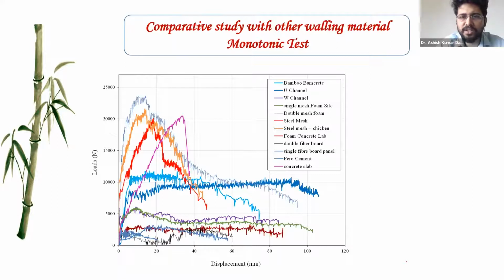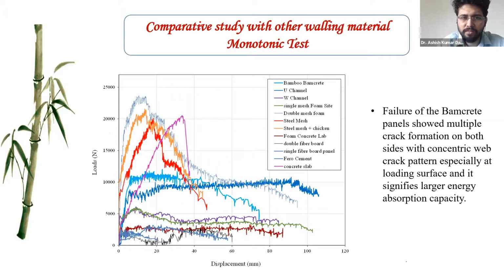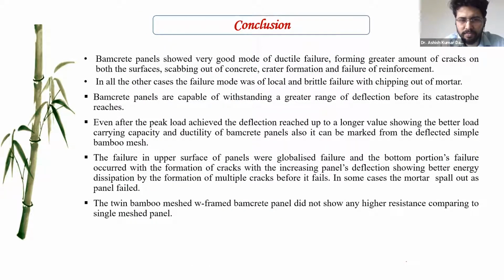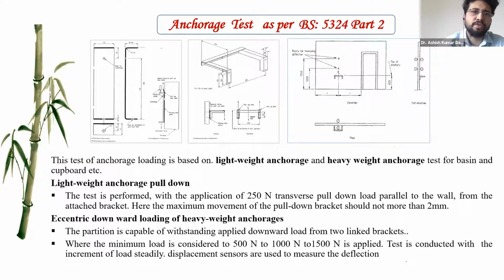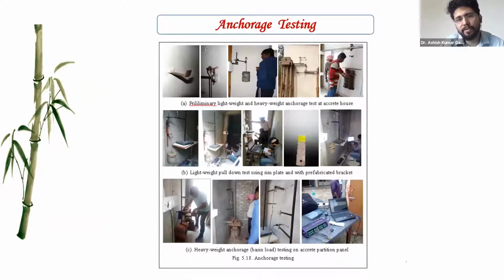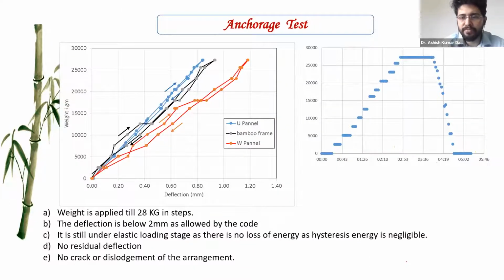For panels like steel wire mesh or the welded steel mesh panel, we found the strength is quite comparable. After this test, we also conducted the anchorage test. The anchorage test is very important: the lightweight anchorage pull down test and the heavyweight anchorage pull down test. That is the basin test. We conducted the test to find out the eccentric loading strength of the concrete panel system, and this is the pattern we found.